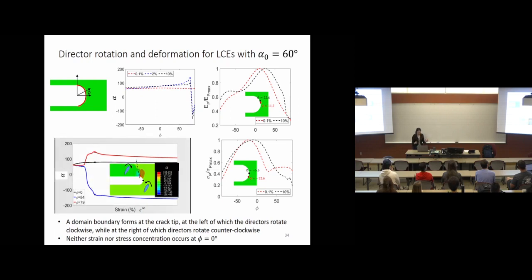So what the result is telling us is that we actually observe a domain wall. On the left-hand side of the domain, the director rotates clockwise, and on the right-hand side of the domain, the director rotates counterclockwise. On the right-hand side, I'm also showing you the strain and the stress distribution at the crack tip for the principal strain and principal stress.